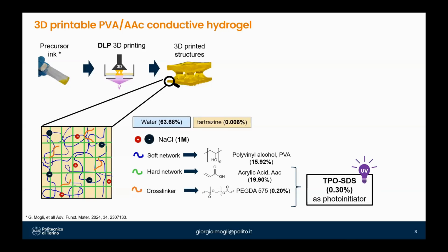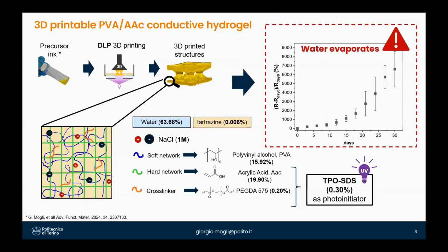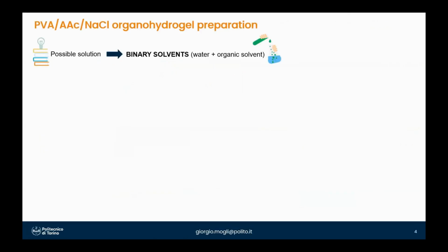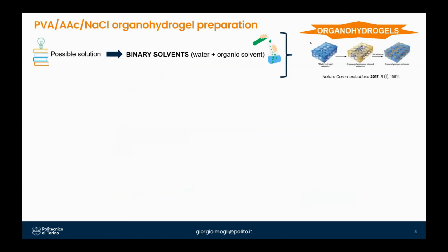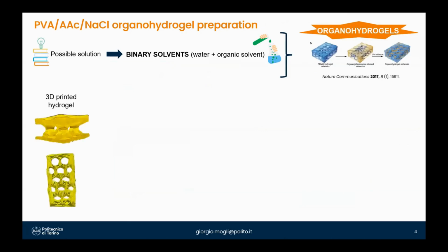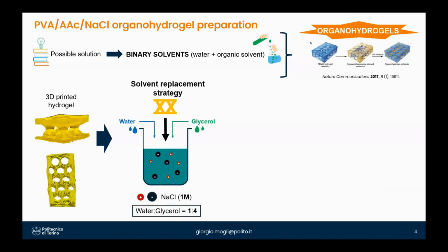The hydrogels were conductive and stretchable. But the main drawback of this hydrogel is that water evaporates. So the electrical resistance is not stable for a long time. So the idea was to substitute part of the water with an organic solvent, a high boiling point solvent like glycerol, to obtain an organohydrogel. So the 3D printed hydrogels were immersed, exploiting a solvent replacement strategy, into a binary solution of water and glycerol, in which 1 molar of sodium chloride was also dissolved.